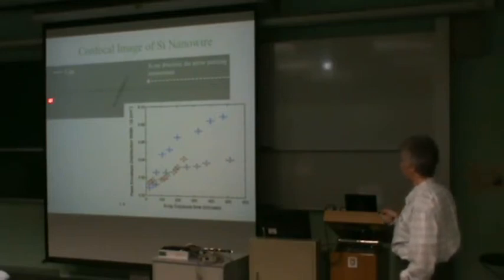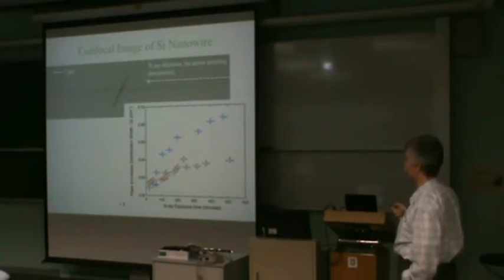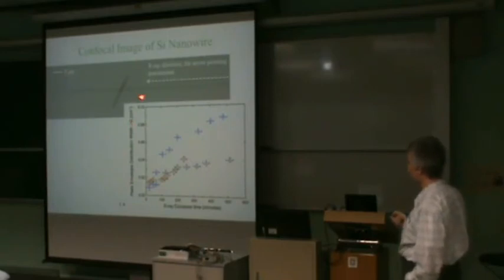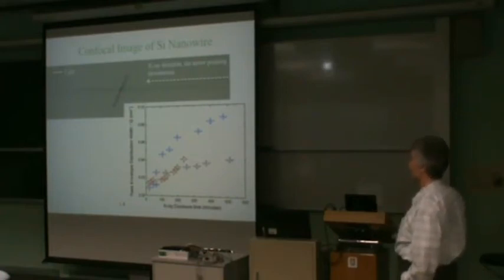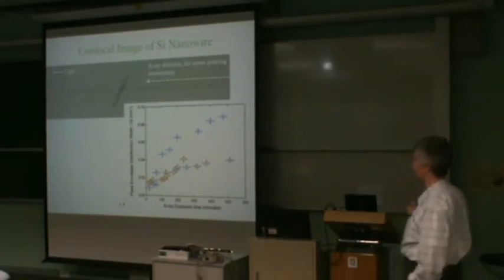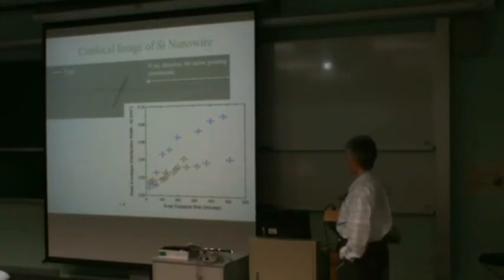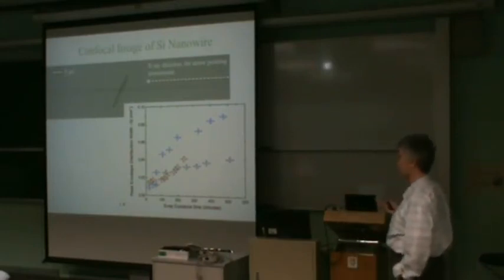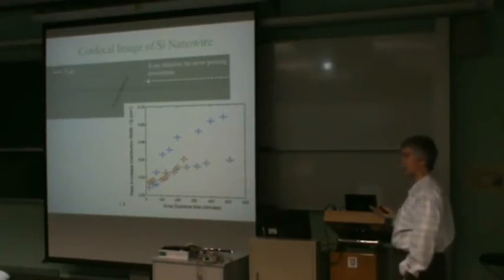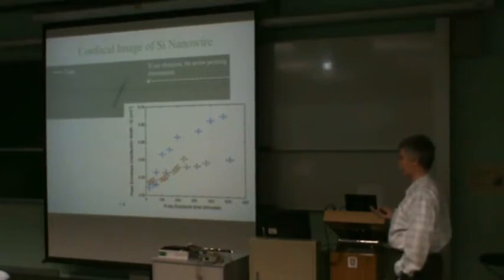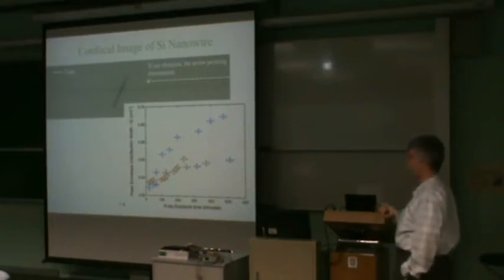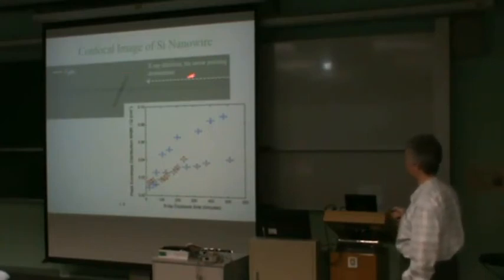In fact, the microscope image that you're looking at here is an optical microscope image taken during the measurements with a confocal microscope. So it's seeing the height of the sample. And obviously, the silicon wire is above the surface, but the fact that you can see where the beam has been hitting the sample means that the oxide has increased in height by some beam-induced damage, which we were able to demonstrate is related to oxygen in the air, because if we replace the air with helium, we get no damage effects. So it's presumably ozone generation by the X-ray beam attacking the substrate and causing a thickening of the oxide in the region where the beam is hitting it.